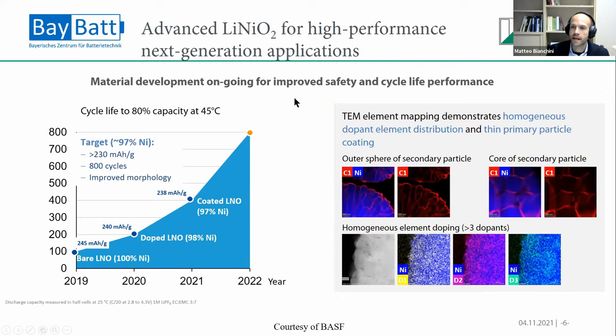So people made the NCM, the nickel cobalt manganese material, by substituting nickel out and putting something else in. But this comes at the expense of lower capacities, lower energy density. And so now with the demand of high energy batteries for automotive application, we need to go back up towards lithium nickel oxide. And that's what's happening. Now we have in most cathode materials in the market around 60 to 80, 85% nickel. And what we did instead was take a top-down approach to start again from the lithium nickel oxide and look at how we can stabilize it by small modifications of the structure.